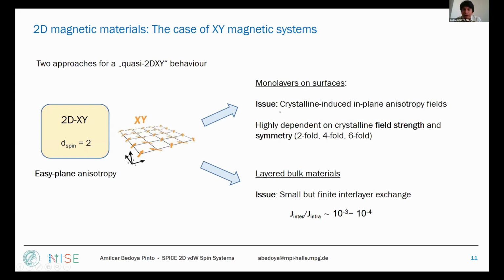So for the case of monolayers on surfaces, we have an issue, which is the strong crystalline-induced in-plane anisotropy. It's obvious to think that you have a very strong crystalline system as a substrate. The monolayer will order according to that, and that would be detrimental for the XY system, because then you will have a preferential orientation given by the crystal. More complicated than that, this in-plane anisotropy is highly dependent on the crystalline field strength and also on the symmetry. If you have a hexagonal or a cubic or a tetragonal substrate, you will have different symmetries and also different crystalline field strengths. In the case of layered bulk materials, when you don't go to the true monolayer limit, you will always have a finite interlayer exchange that precludes treating it as a fully two-dimensional XY system.